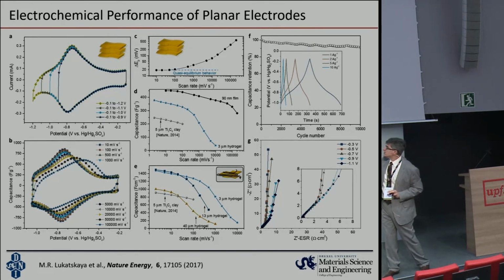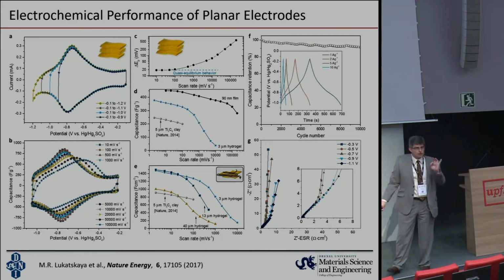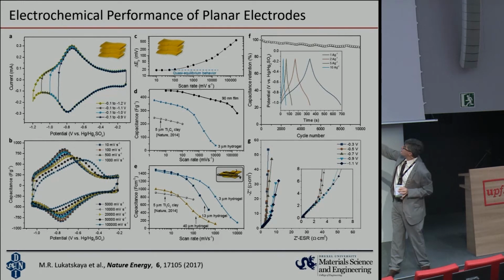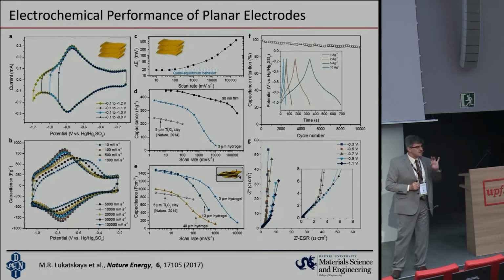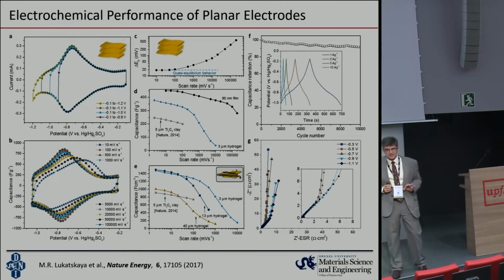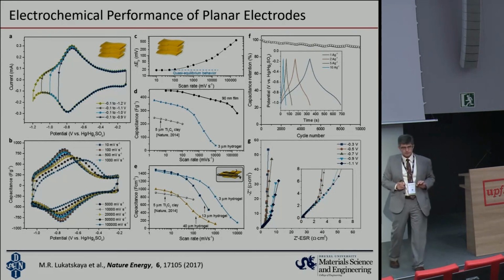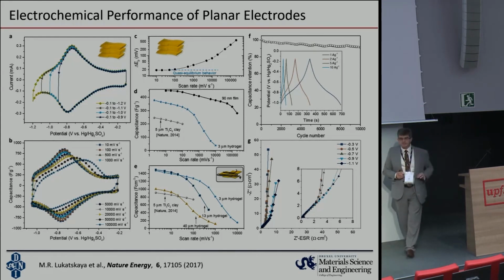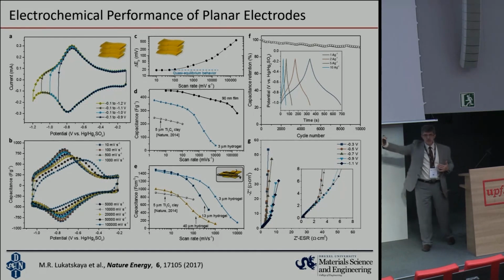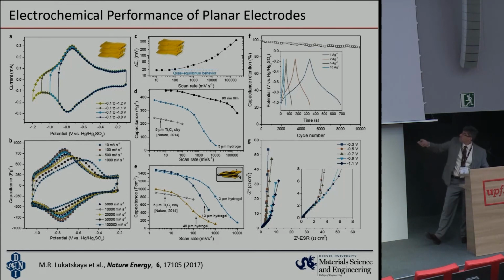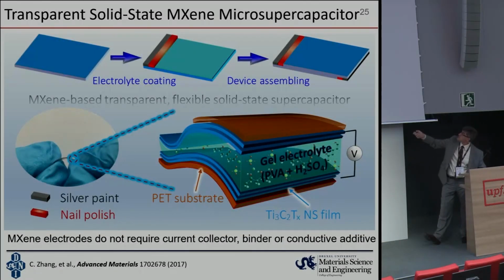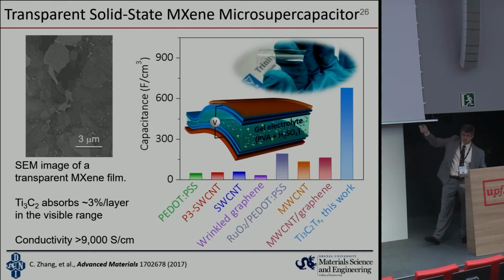We can charge it at actually 100 volts per second, and we only lose about 20% of capacitance. So we can have a redox process operating at rates much faster than even double layer capacitance can give you. It offers a great opportunity for harvesting energy from very fast processes, AC/DC filtering, and many other applications in which the values of charge stored are significantly larger than in double layers. And of course, the thin films can be used to make transparent supercapacitors, for example, that will be flexible, bendable, and so on.